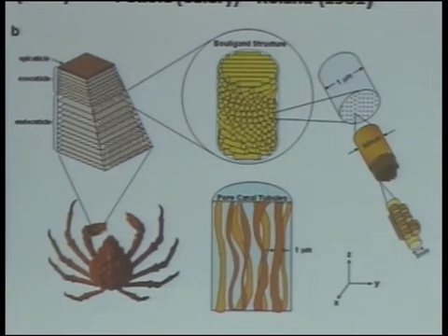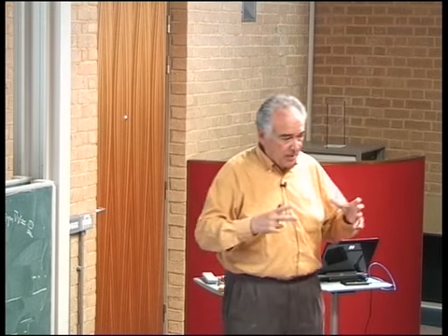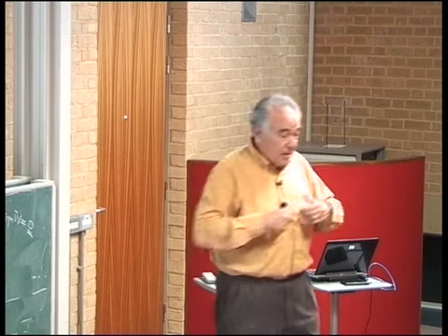And the interesting point is, in terms of chirality, as you go from a primitive object, which, for example, is 3 molecules, so that's a coiled coil structure that assembles with another triple helix, that object is changing chirality from left-handed to right-handed. So each time you have this aggregation, the chirality remains but changes sign. That's a key concept here. The chirality doesn't wash out